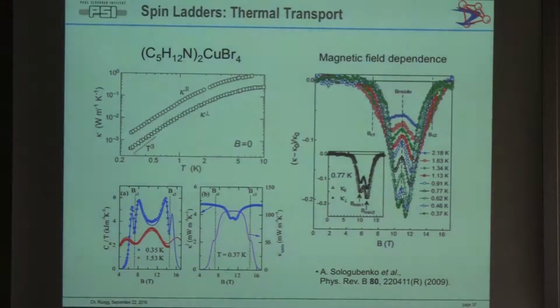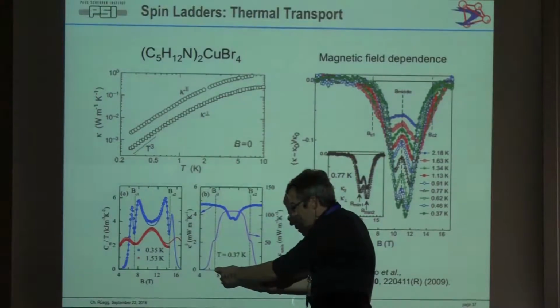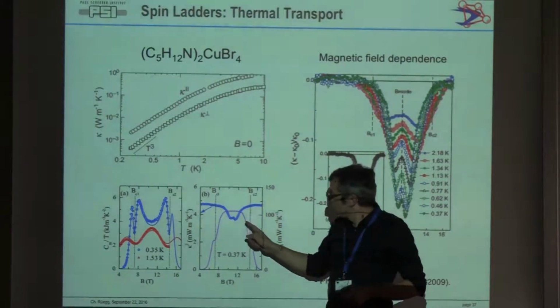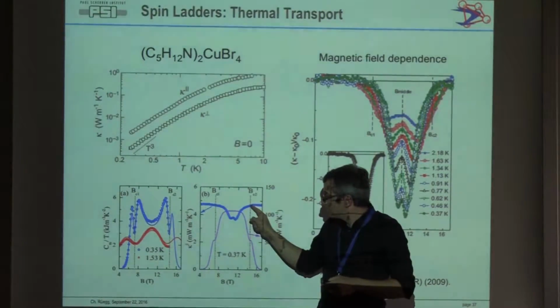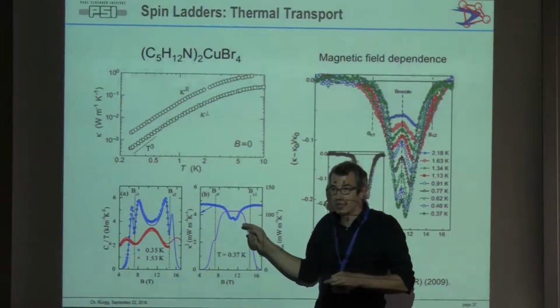Okay, so there are these critical fields below which at very low temperatures there are no magnetic excitations. Yes, that's right. But in the middle range, about 10 Tesla or so, the discrepancy is much smaller, where you expect the finite population of your magnetic excitations. Yeah, true, but it completely doesn't fit. First of all, the critical fields are here. We know them exactly. You see where the action should start here. That's somehow true. Where you have a big double peak structure here is another question.